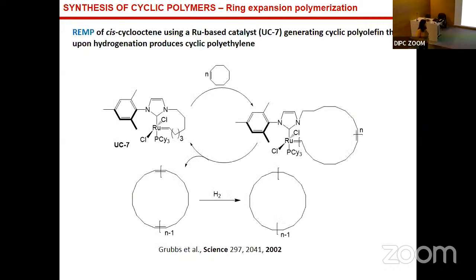I brought some examples. This was the first example, where a ruthenium catalyst was used for the generation of a cyclic polyolefin by Robert Grubbs in 2002. He demonstrated that this process is efficient, produces a high amount of cyclic product, and allows us to synthesize a cyclic polyolefin that was not possible before. This is a kind of ring expansion metathesis polymerization. This is an example of this.